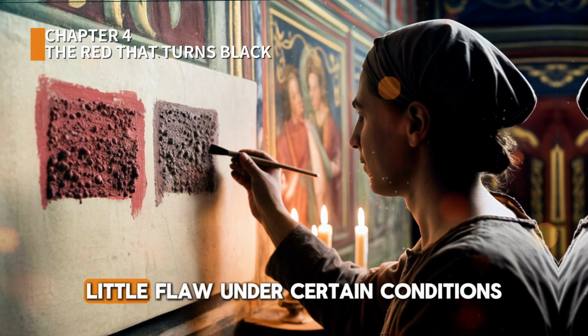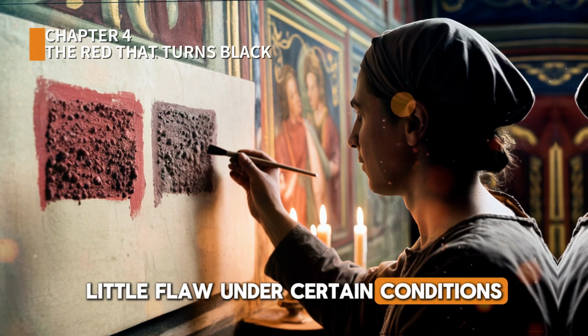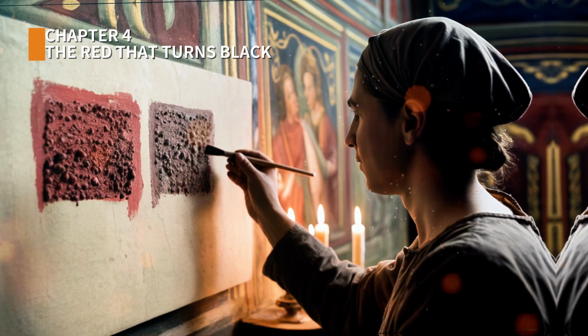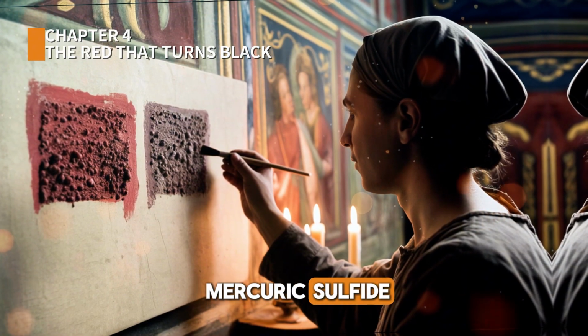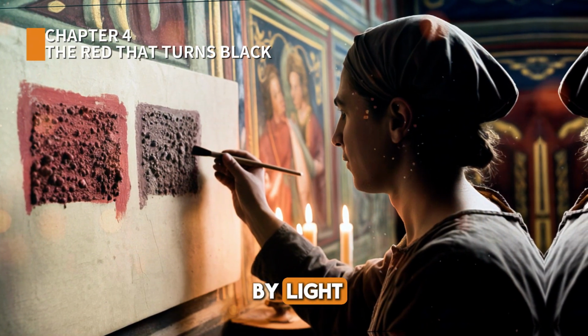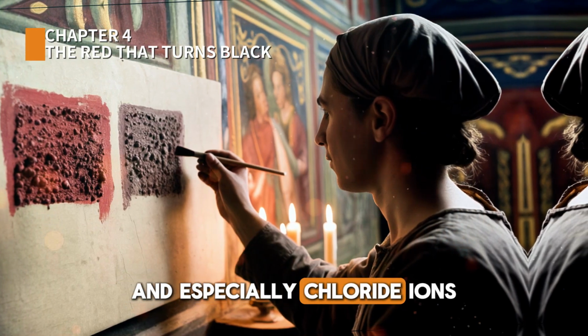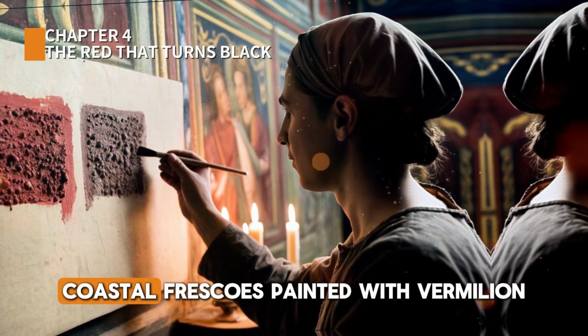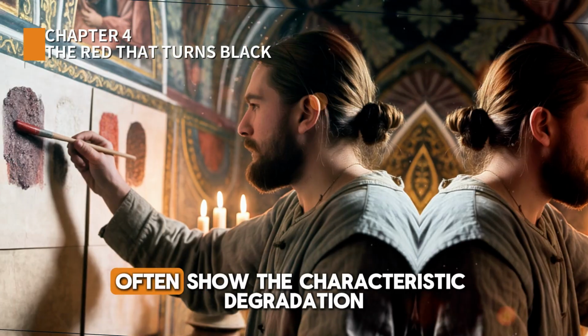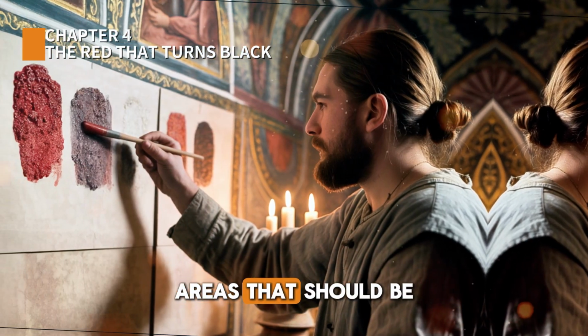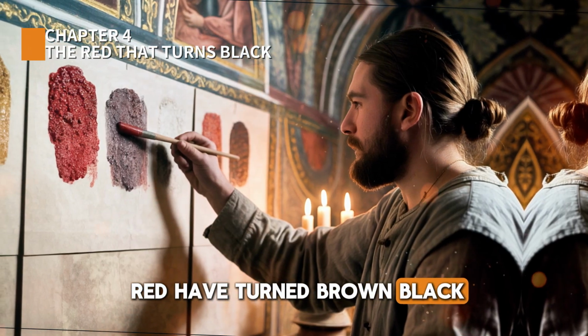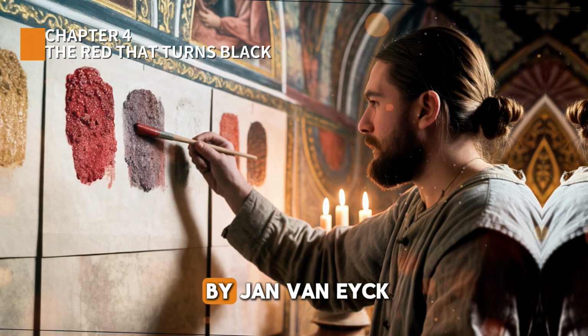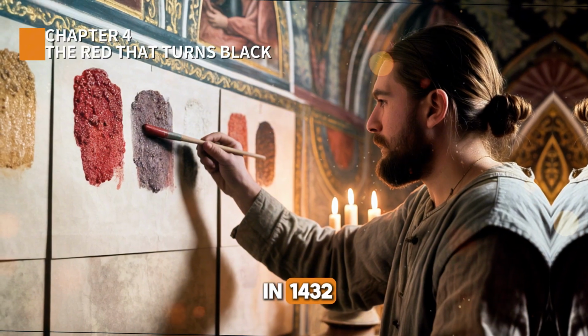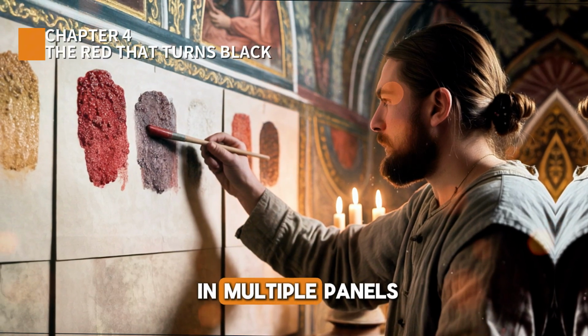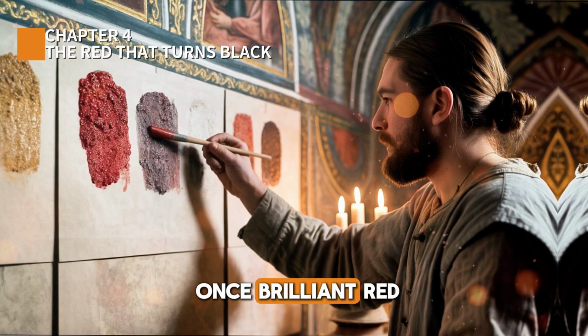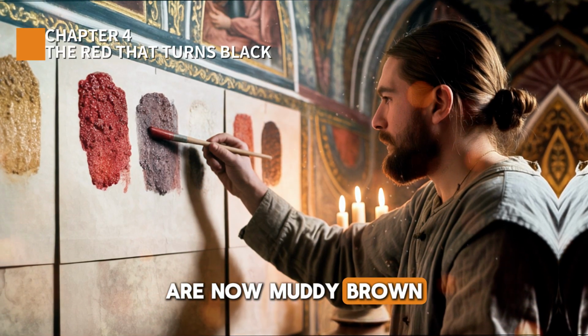But vermilion has a fatal flaw. Under certain conditions, it converts to metacinnabar, a black form of mercuric sulfide. The transformation is triggered by light, humidity, and especially chloride ions from salt exposure. Coastal frescoes painted with vermilion often show the characteristic degradation: areas that should be red have turned brown-black. The Ghent altarpiece, painted by Jan van Eyck in 1432, has suffered vermilion darkening in multiple panels. The robes that were once brilliant red are now muddy brown.